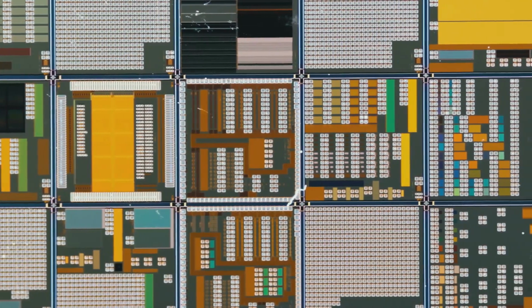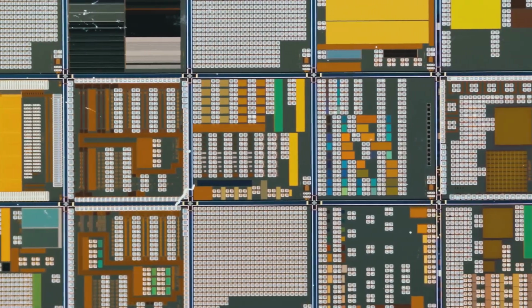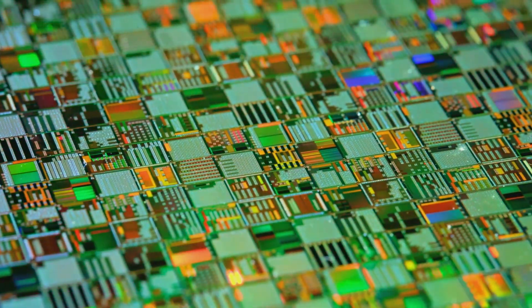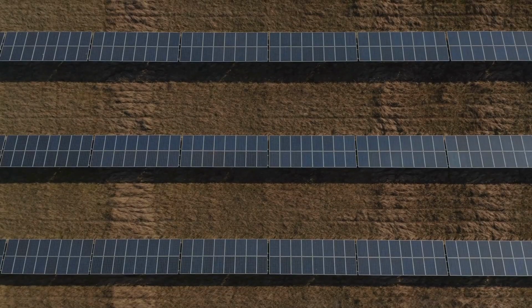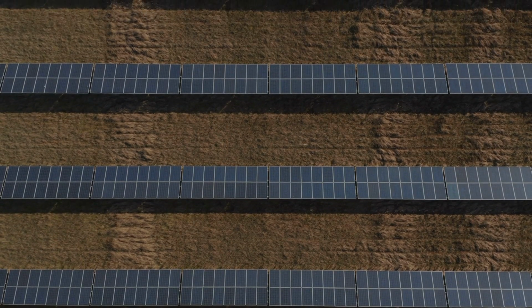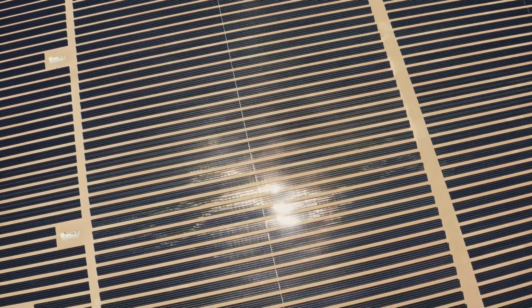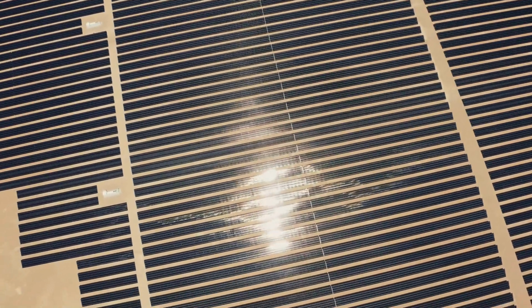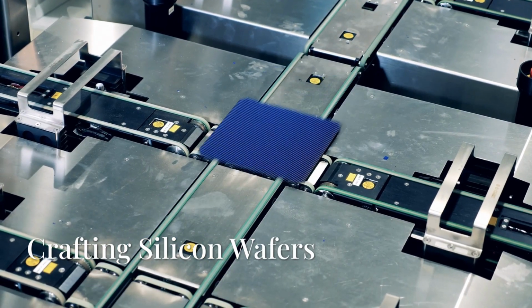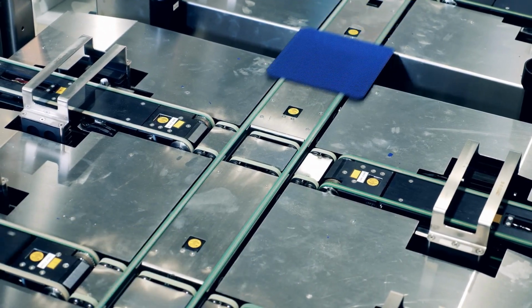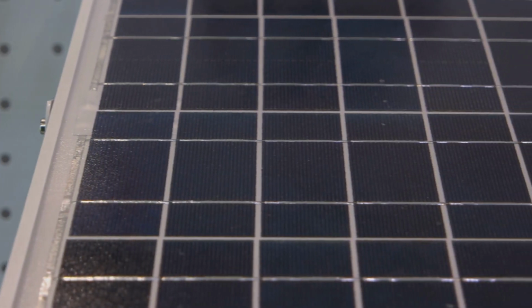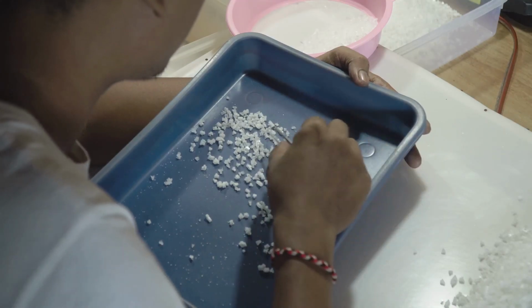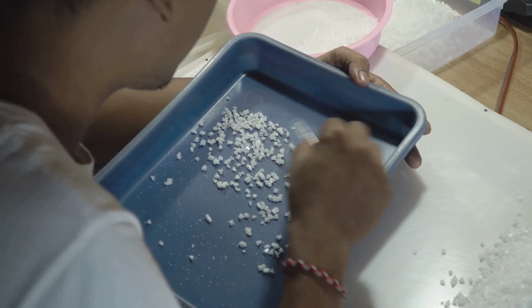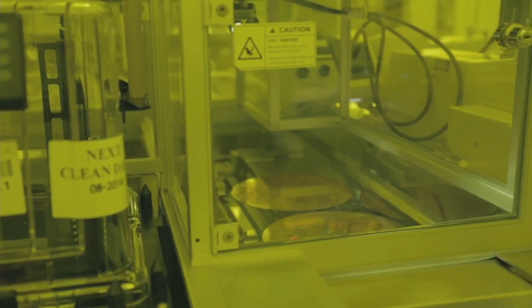The Czochralski process creates a long cylindrical crystal called an ingot. This ingot can be over 2 meters long and weigh hundreds of kilograms. Every atom inside is aligned in a single, continuous lattice. This perfect order allows electrons to move more freely, which means higher efficiency when converting sunlight to electricity. Whether a perfect cylinder or a solid block, the silicon ingot is now complete. It is a dense, heavy piece of highly purified, crystallized silicon, but it is still too large, too thick to be used in a solar cell.